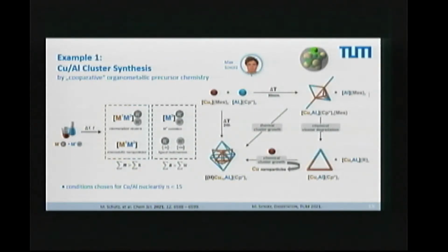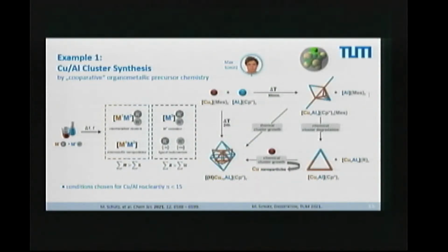Now I walk you through this synthetic diagram. So what is shown here? Here is shown the organometallic chemistry we are doing. Now this is basically because all our chemistry would die if we do it under ambient conditions. We must go under nitrogen or argon atmosphere into a glove box and avoid any trace of water. If there is oxygen or water, we get oxides, no molecules, no clusters, everything is dead. So it's a very sophisticated organometallic synthesis chemistry going on. Then we have two components, the metal 1 and the metal 2, and the R means this is just the organic coat that I introduce when I start with these components. These are components we can synthesize. Some of these components we can buy from chemical companies, but what the chemical company can give us as a precursor compound for this chemistry might be too stable.